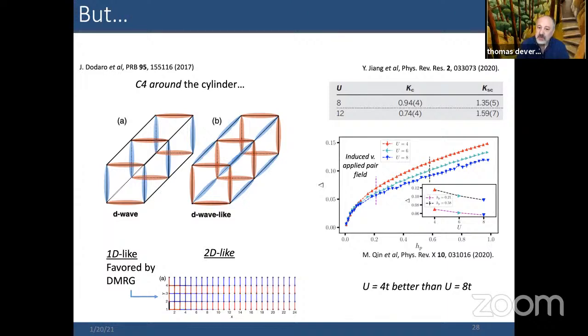And then the other is if you look at different values of U, for U of 8 or U of 12, you find that the superconducting correlations drop off faster for larger U. That's also shown in this figure from this other paper, which again shows that U of 4 seems to have a stronger tendency to superconductivity than U of 8. And the DMRG shown in the upper gray area shows that the correlations are dropping off faster for larger U. So this is going to be the question of whether in the region where we would like to see it, we have enough superconductivity, even in the case where we see long range superconducting order. And I'll come back to this.